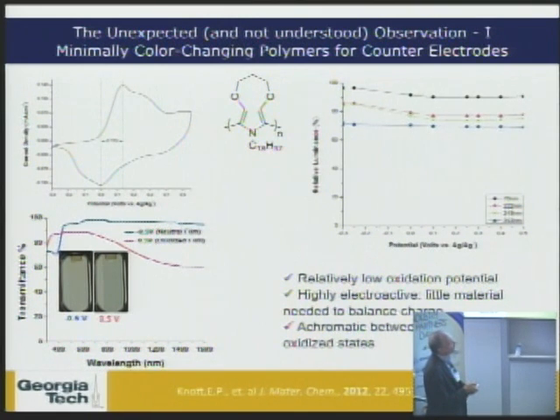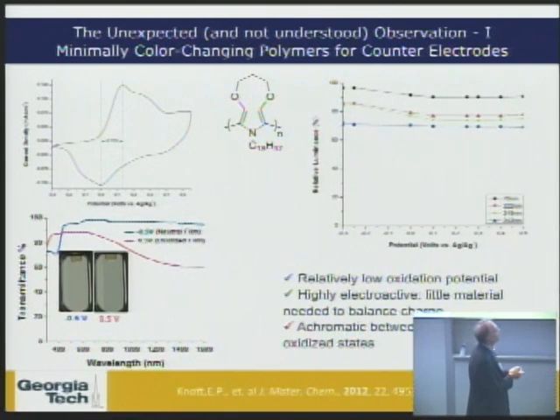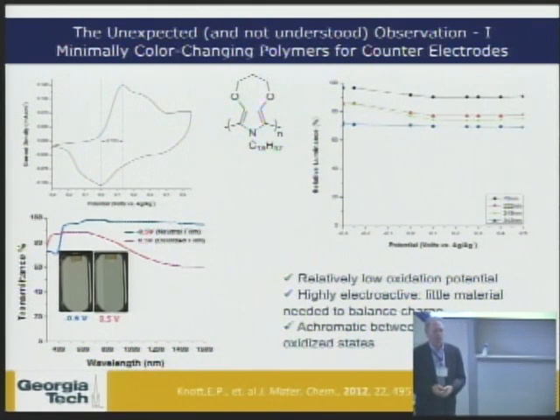But what we were surprised to find was that we saw very little change in the color of the material upon oxidation. You're looking at the transmittance here, and you can see that the onset of the pi to pi star transition for the neutral polymer is here right around 400 nanometers, and so the film is very transmissive to your eye. But upon oxidation, you end up in the fully oxidized form having well over 80% transmission through the visible range, and most of the change in the absorption is in the near infrared.